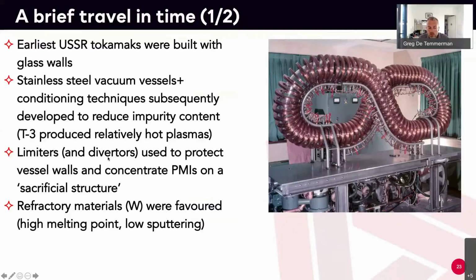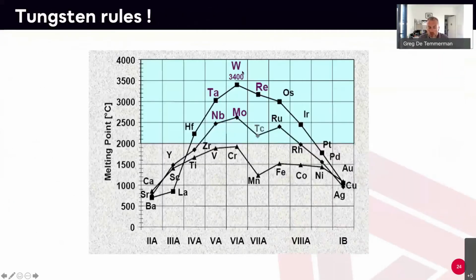Then people decided to use different kinds of structures to isolate the vacuum vessel from the material itself, which was in contact with the plasma. And at that time, people said, well, we want a material which is as resistant as possible, which has a very high melting point. So when you look at this plot, looking at the melting point of different metals, well, the king is tungsten. Basically, it melts at 3,422 degrees Celsius. So that's the better choice to go to. That's the most resistant pure metal that you can actually find.